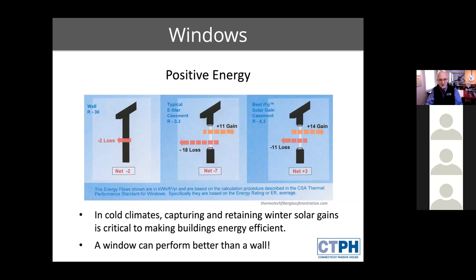And into that wall, we stick an Energy Star casement window. In other words, R3.3 overall. Now we've gained the view, the light, and we gain in the sunny days, we gain a plus 11. But we're still losing minus 18. In other words, we're losing more than we're gaining. So we've gone from a net loss of 2 to a net loss of 7 by that window. But let's flip the formula here. Let's put a window in that's R, say 5.3 overall.